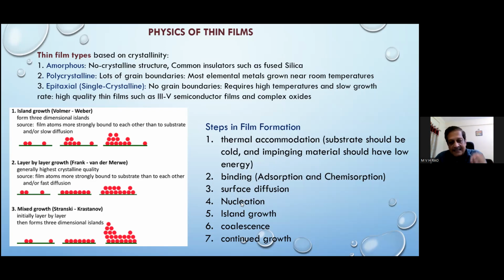Normally, if there are certain defects, they get stuck at the defects. If there is a step on the substrate, or a small crack or scratch, first it will decorate all those locations. These atoms get stuck there, then the next round of atoms will come and get stuck at that place. So these are nucleation centers. The defects on the surface act like nucleation centers, or the dangling bonds, if the surface is activated by chemical etching so that there are unsatisfied chemical bonds on the surface. Then immediately the adhesion will be better. So these are some of the techniques we have.